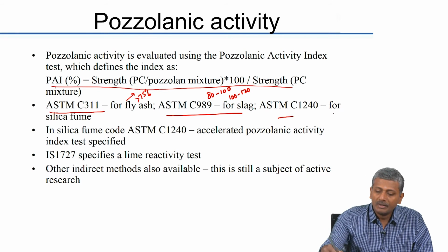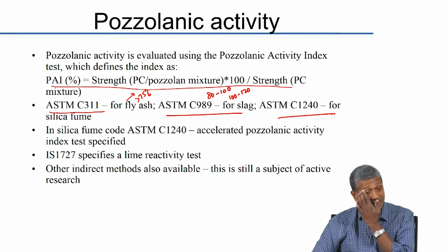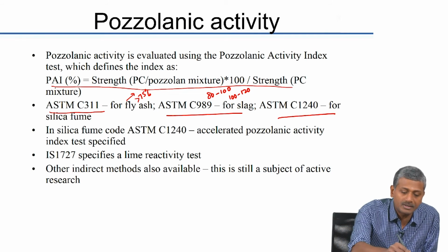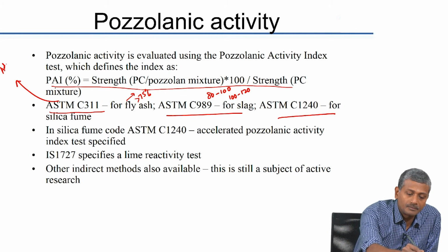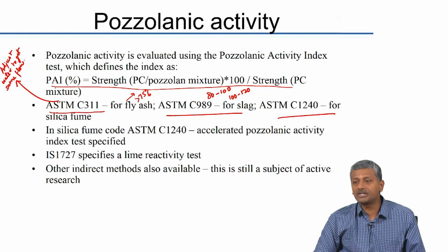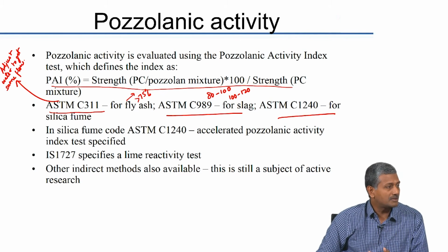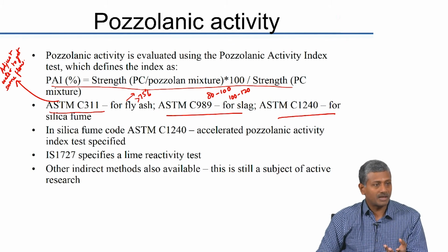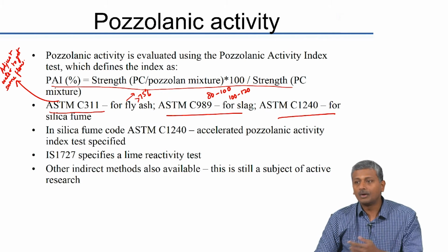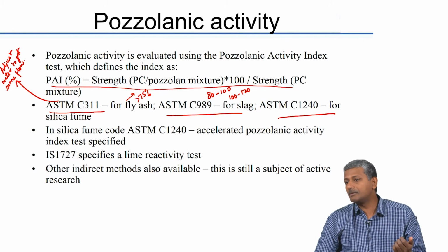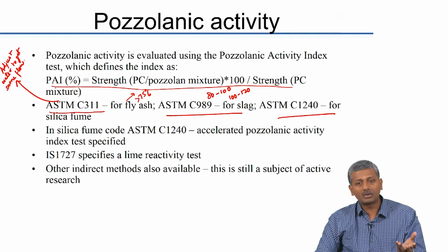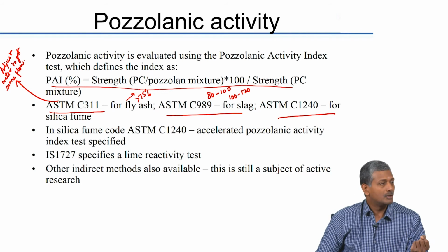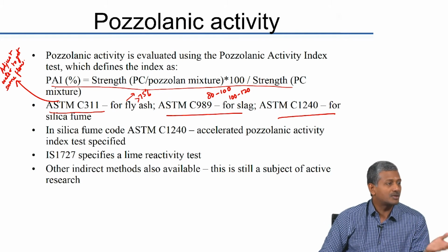And for silica fume, we use a slightly different standard. There is a reason for that. In your ASTM C311 standard, we adjust the water to get the same flow. That means if I am replacing cement with fly ash and my water requirement is higher to obtain the same flow, my fly ash mixture will actually have a greater water content than the cement mixture. Or alternatively, if my workability improves with the addition of fly ash, my water requirement for the fly ash system will be lower, so my water cement ratio for the fly ash system will be lower than that of the cement system.